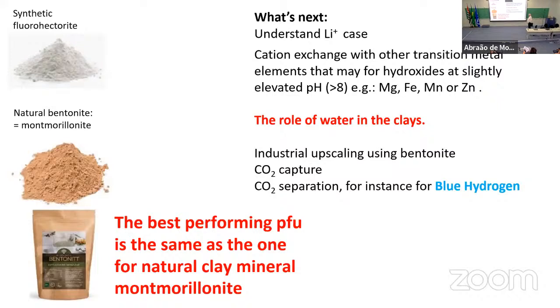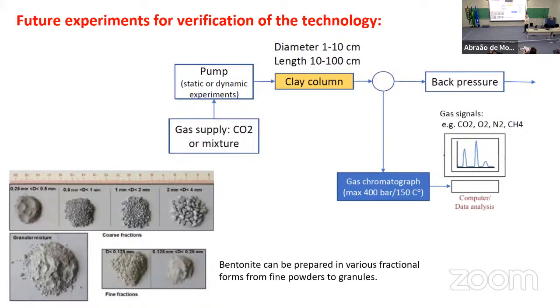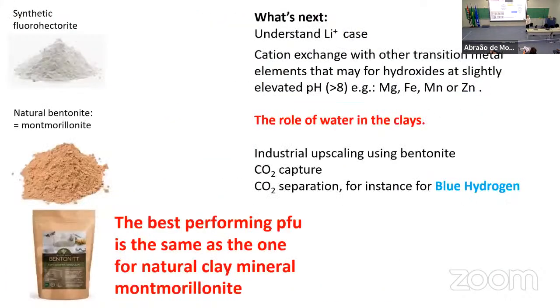So how can you get something in applications out of this? The clay we have studied is a synthetic clay. I mentioned that the optimum surface charge is the lower charge. That lower charge is the same charge as we find in the natural clay called bentonite. So the upscaling of this into industry would be to repeat these experiments, and we are actually in the process of doing that, using natural clay bentonite instead of the synthetic clays we have been using to understand what's going on. So now we think we have understood it. Now we can use it.